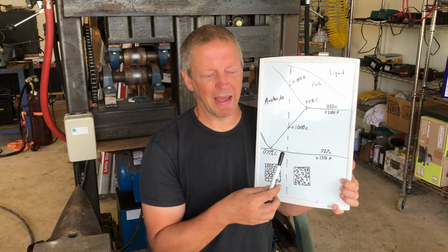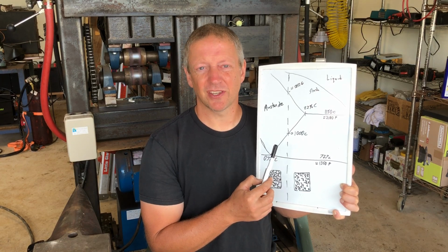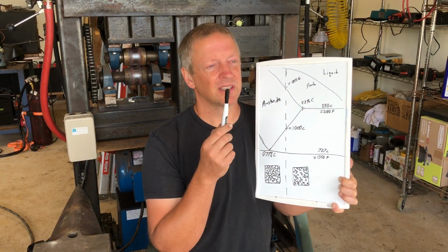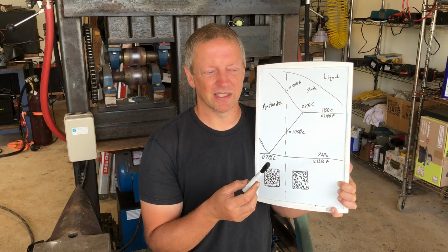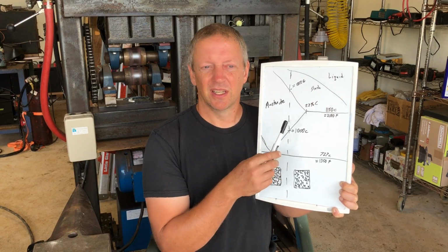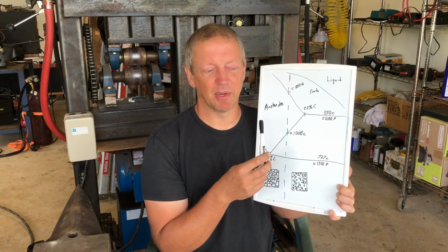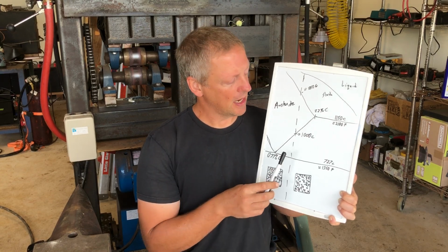The good thing about this type of fracture is that it can be avoided as long as you don't hit the steel at that temperature, while it's in that state. So if you've overheated your steel, you realize it, and you let it cool before forging it, you should be okay. I'm not going to say you're going to be okay. Nothing's 100% certain.